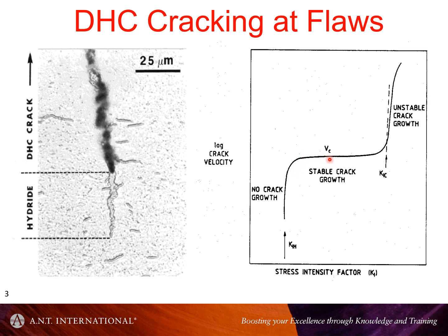Of course, the stable crack growth is dependent on the size of the crack, but also on the rate at which hydrogen gets there. So, in terms of a crack velocity, it cracks at a certain rate. Once you get cracking going at a certain load, it'll accelerate, or eventually accelerate, as the crack exceeds its critical crack length.